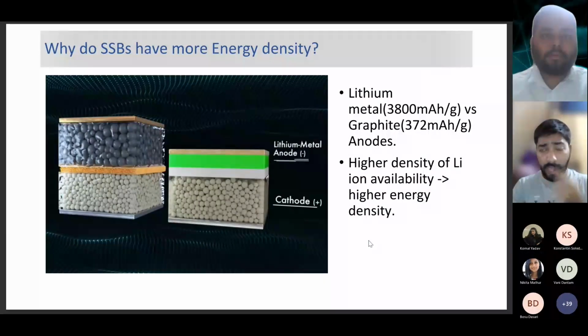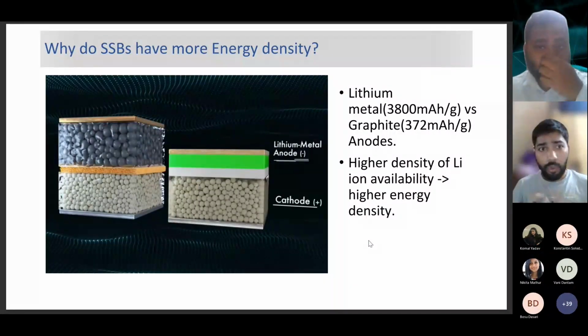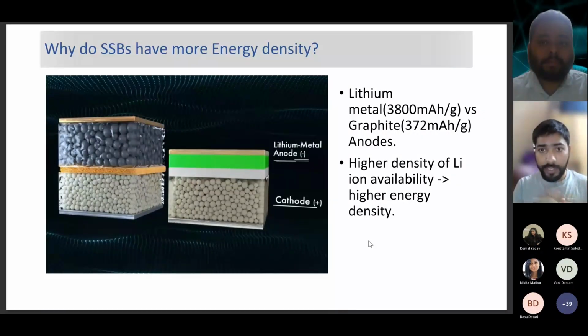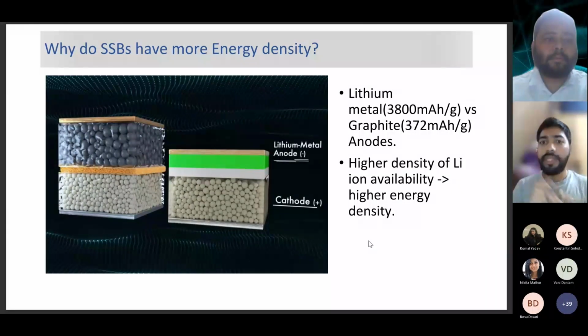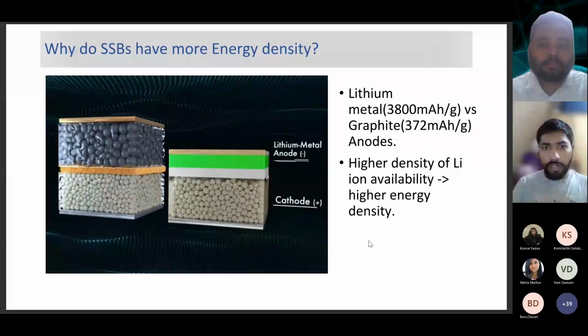So we saw how the ions are going to move, but why do solid state batteries have more energy density? And this we have also seen in previous sessions by other people, where they mentioned the energy density difference. If we are using lithium metal, it has almost 10 times the capacity of the graphite that's currently being used. If you compare graphite anodes and lithium metal anodes, you can see the difference in size at the cell level itself. So we are able to reduce the thickness on the cell level if we are comparing the same sizes.